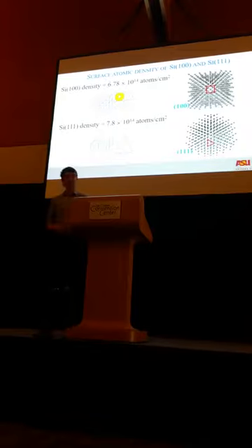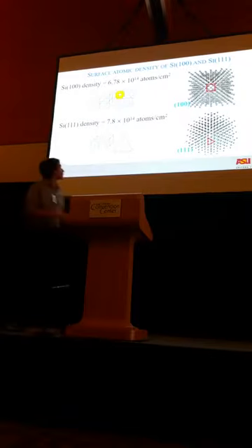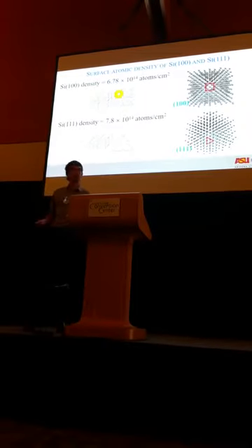So what is the difference in surface atomic density between silicon 100 and silicon 111? We can see in this first image our orientation of the silicon 100 crystal, and we can see that the corresponding vector is normal to the face of the cubic silicon crystal. In this orientation, silicon has a surface atomic density of about 6.78 times 10 to the 14 atoms per centimeter squared.